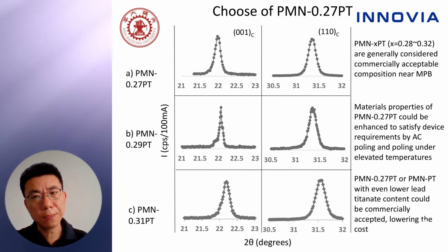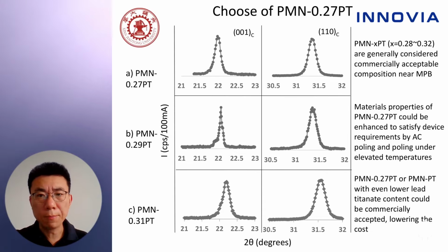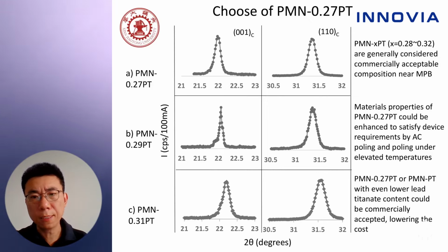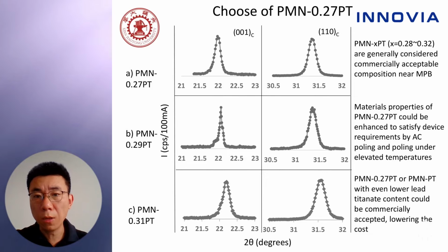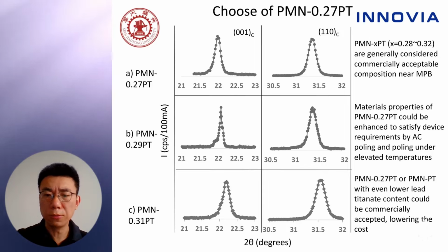Now, 28% PT to 32% PT are generally considered commercially more acceptable, near MPB. The material properties of 27% PT, if they could be enhanced to satisfy device requirements by AC poling, then 27% PT or lower PT content of the crystal could be commercially accepted. This will lower the overall cost of making transducers.